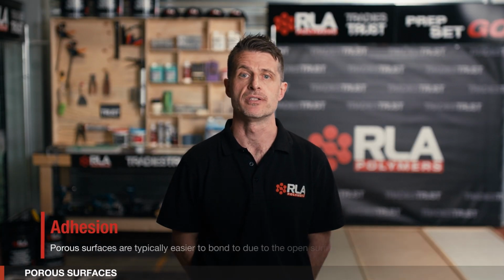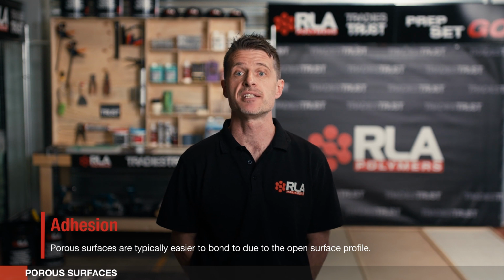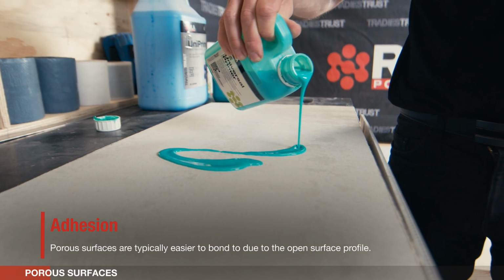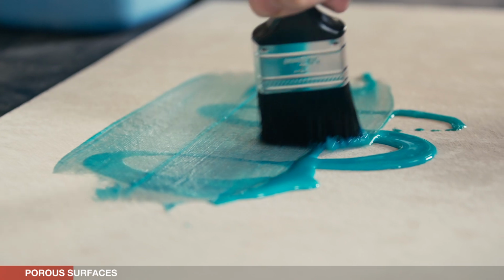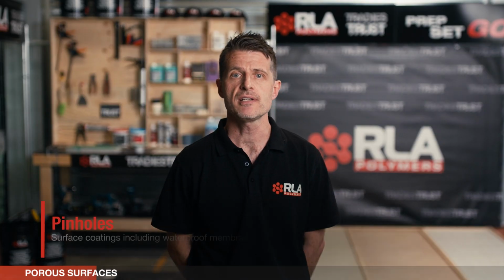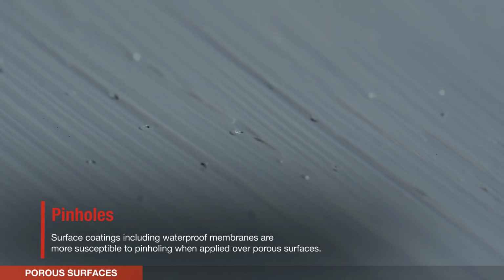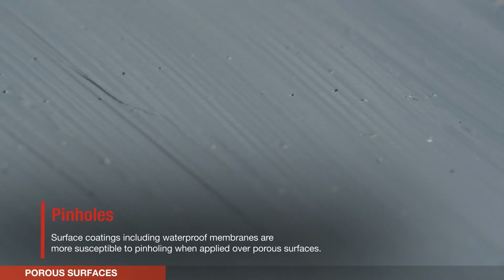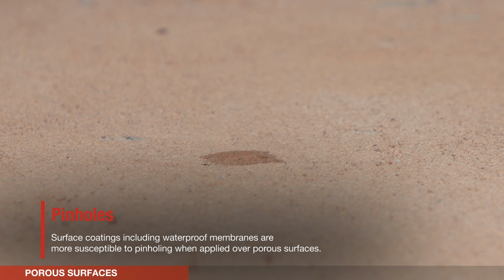Number one, adhesion. Porous surfaces are typically easier to bond to because of the open surface profile. On the flip side, however, liquid coatings, including waterproof membranes, are more susceptible to pinholing when applied over a porous surface. This is due to the rapid absorption and drawing down of the moisture contained in the material into the actual substrate. Pores of concrete contain air and become trapped when the coating is applied over it. The trapped air then tries to escape, pushing up against the coating and creating these small pinholes.